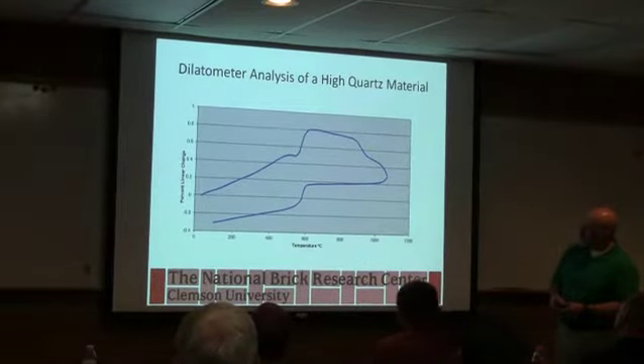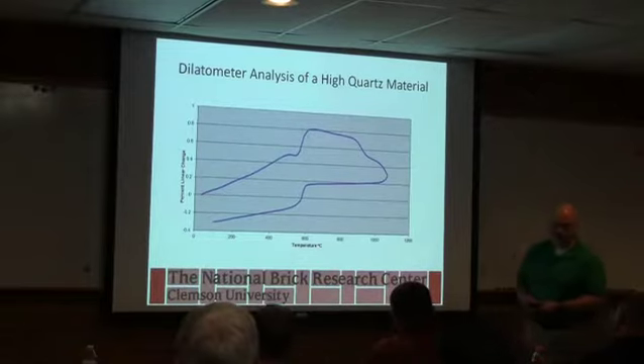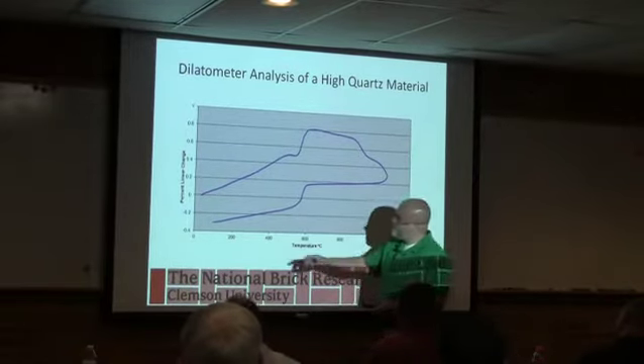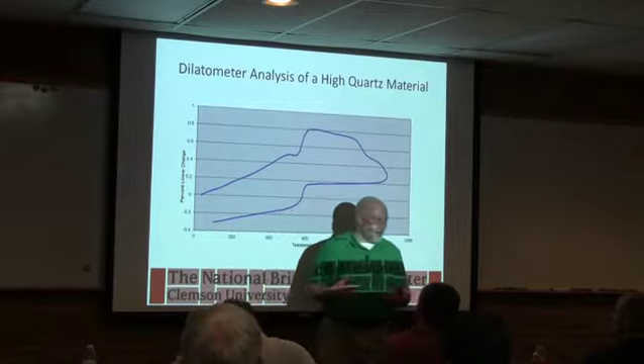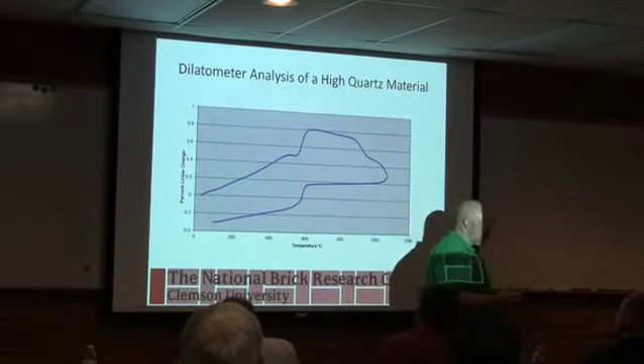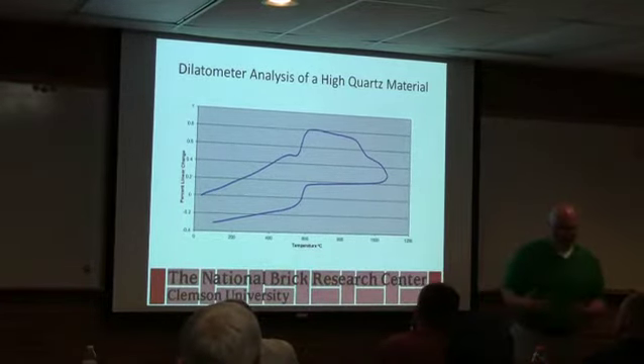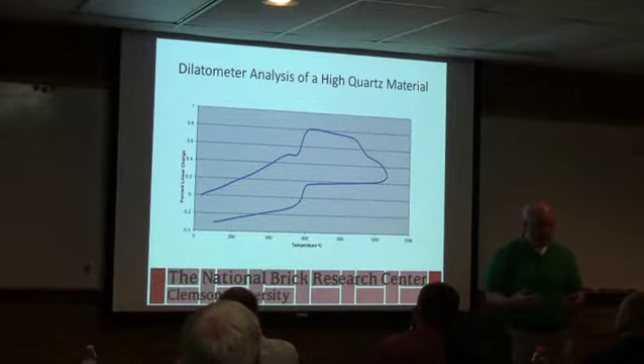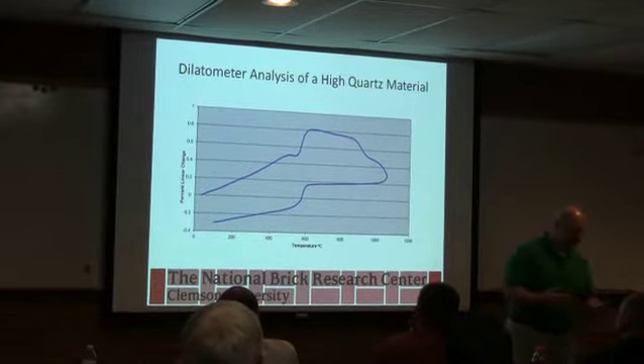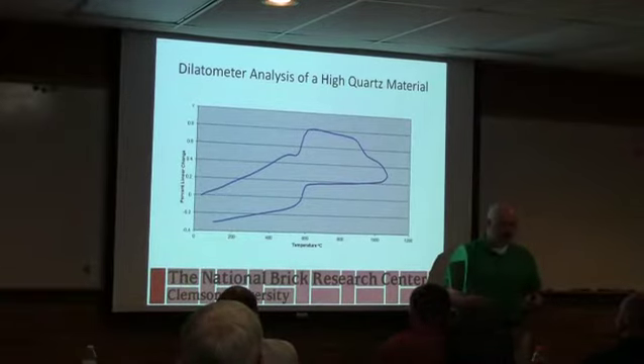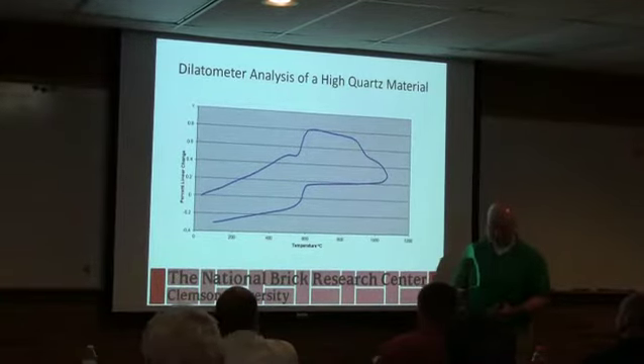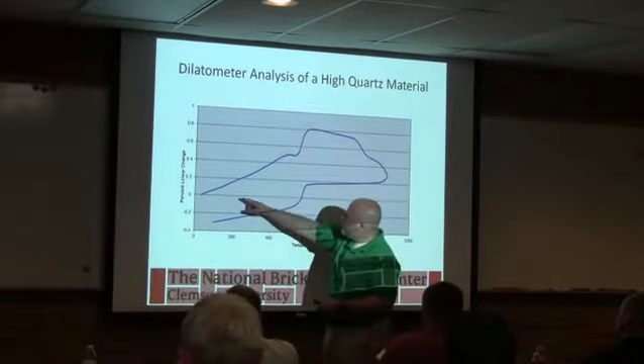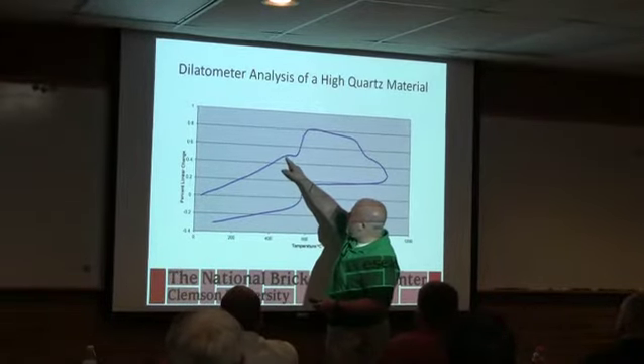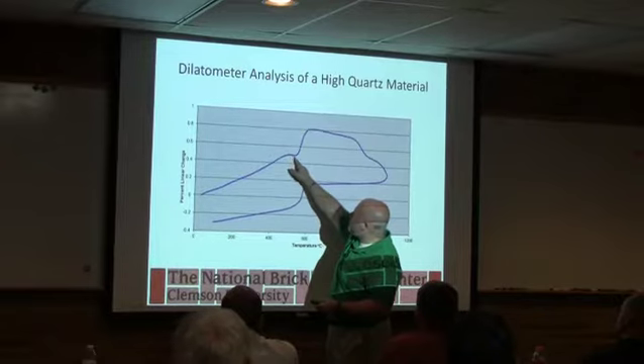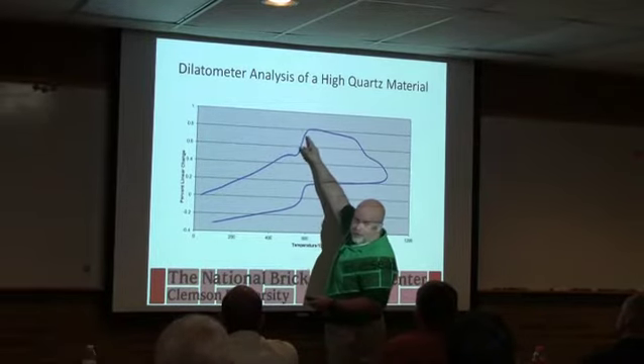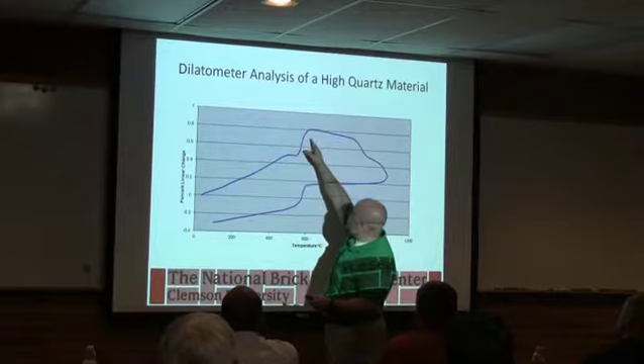So this is a dilatometer curve for a very high quartz material. It looks kind of funny, but what you're seeing here is, everything has expansion. So when you're building a wall, typically you're going to put in an expansion joint, right? Just from normal heating up during the day. Everything does that. So your brick on the car, as you're heating them in the kiln, are growing just because of thermal expansion. So we see thermal expansion up to a point where probably the clay mineral's decomposing, and then we go alpha to beta quartz, okay? And you get a big jump.